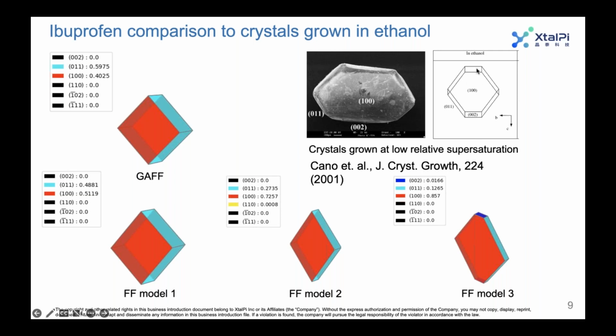So you can think of this as the true morphology of ibuprofen that we would expect from ethanol based on the experimental growth rates. In the top left corner, I have the morphology prediction obtained with the GAFF force field. You can see it doesn't match terribly well with the diagram on the right. However, it does have some of the aspects correct in terms of the faces.